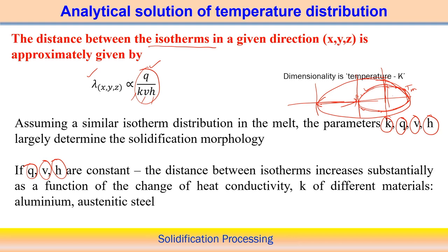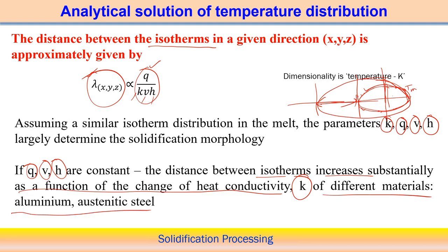Therefore, the distance between the isotherms, which is characterized by this value of lambda, increases substantially as a function of the heat conductivity, as a function of K. So K is the more influencing parameter here to change the gap between the two isotherms, or the shape of the isotherm, if we keep the other parameters the same. We will be able to see the influence of the thermal conductivity for different materials. So we compare aluminum and stainless steel. We know that aluminum has very good thermal conductivity as compared to austenitic steel. So there is a huge difference in the thermal conductivity value.